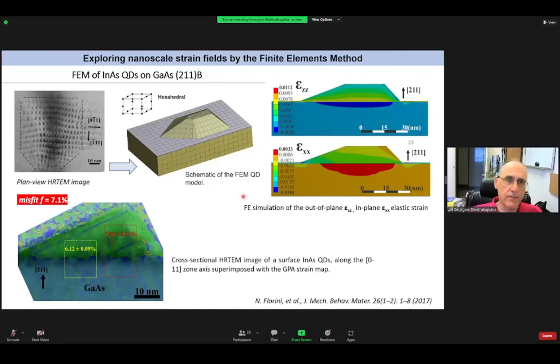Now, regarding strain fields in general, I told you earlier that instead of atomistic calculations, you can use also finite element analysis. You can indeed employ such an approach, which is a continuum approach. It's not an atomistic approach, but we have shown that it works very nicely at the nanoscale, and we have used it for quantum dots and for nanowires, for example, and we were able, with the finite element analysis, to quantify the strain fields that we were observing.